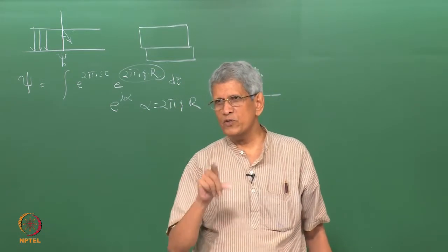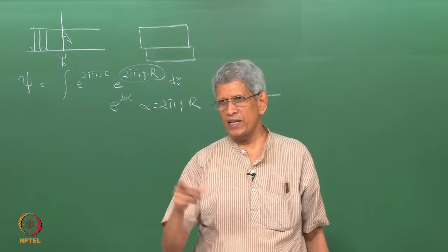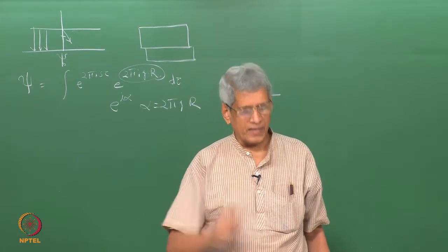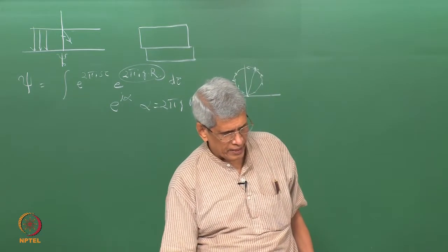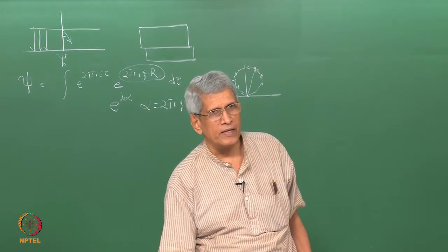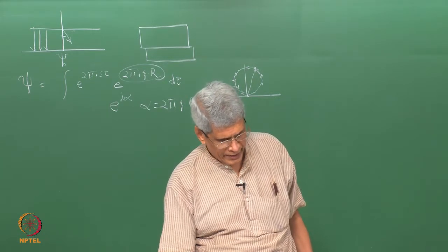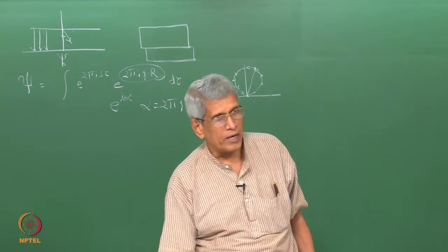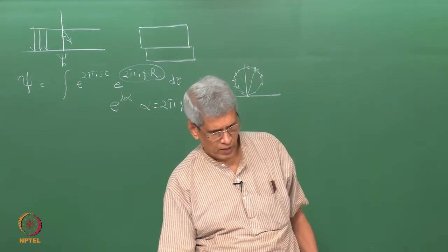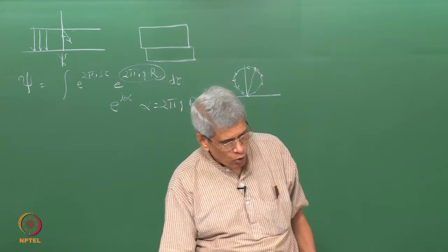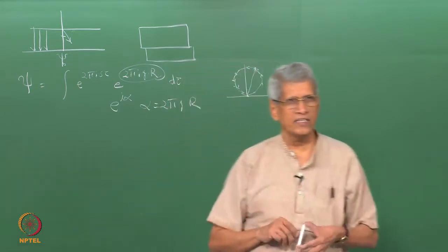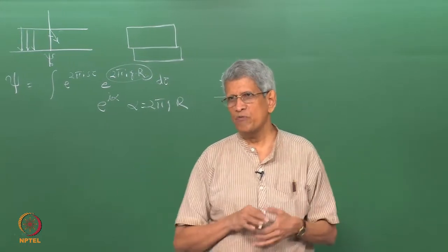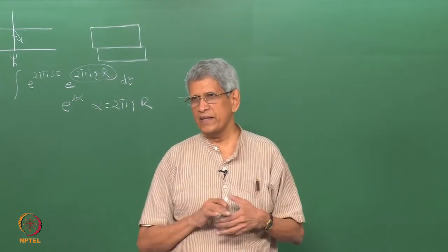This will give rise to a variation in the phase, and finally when we look at the amplitude and the intensity, here it will add together because you do not see the defect, and at this midpoint there is a phase difference of pi, so the intensity will become 0. Here again it will add. Though the lattice separation is small, we are now able to get a fringe spacing which is much larger than that.